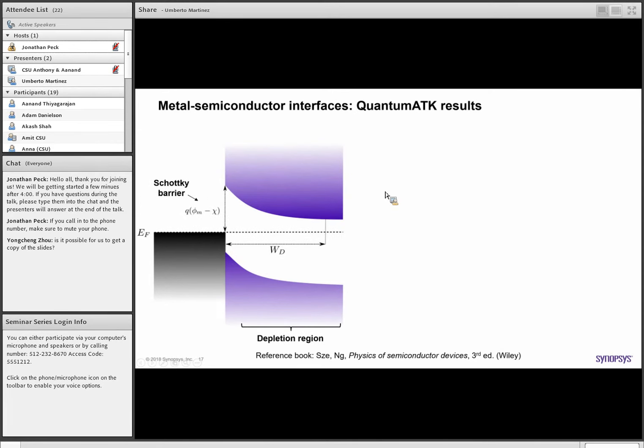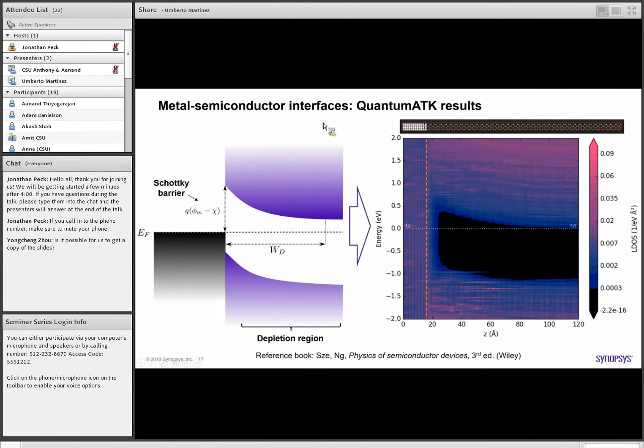And let me just show with the methods that I described before. These are results that are done with DFT. And those are the results for, you see in this upper picture, the model used to calculate this density of state plot. We have a silver and an n-doped silicon. So you see that what we get out of this simulation is really like a metal semiconductor fingerprint.